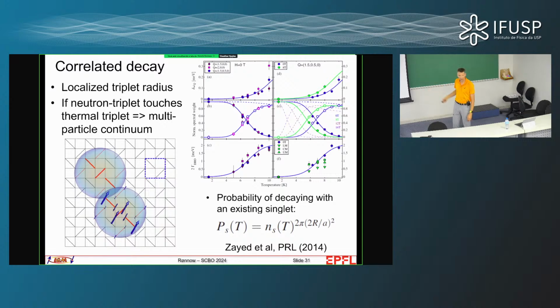This extremely simple model, I would barely call it a theory because we haven't calculated anything, we just make a hypothesis. That's a line which goes through our data points. We can apply a magnetic field and split the triplet so that one side of the triplet goes down to lower energy, so we change the gap. And if you change the gap, then the temperature dependence changes, and it again agrees with experiment. Okay, so it's not actually a theory; it's just a hypothesis, but it happens to describe the data. So I'm hoping that theorists will eventually catch up and either prove that there's a completely different reason which accidentally gives the same curves, or that our argument is a good one.